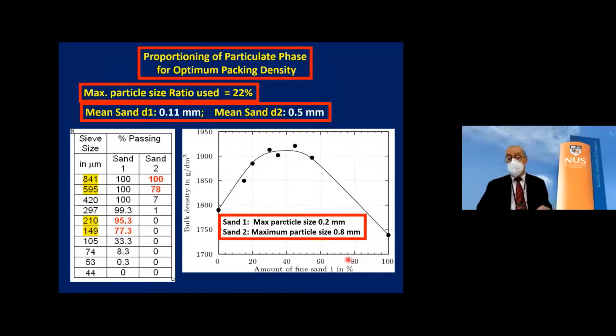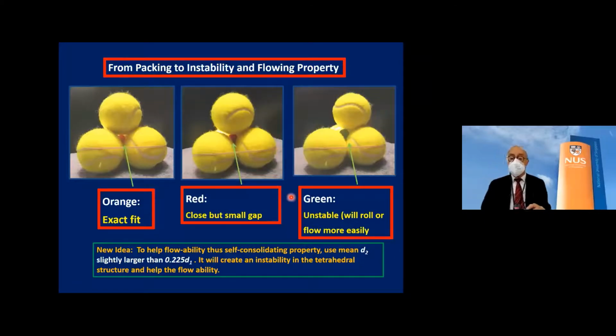And one more thing, that something more is that you will pick up 2 sands, for example, sand 1 and sand 2, and you find out that each one may have a bulk density, but when you mix them together, there is a proportion that is going to give you the highest bulk density. And so we needed to pay attention to that in our calculation. The other thing that we did that was, I think, a little bit innovative is that we selected the sand that went in here. We gave it a little bit of a bigger range.